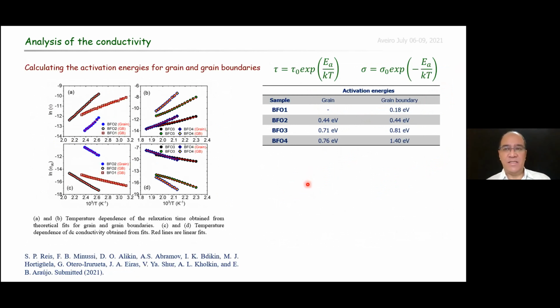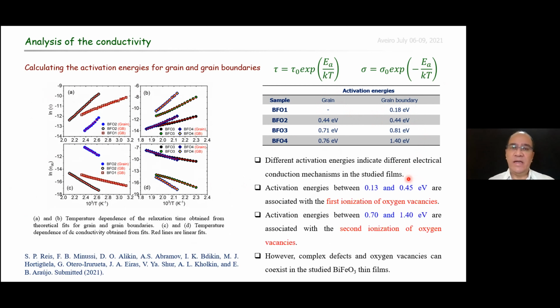From all these analyses, the temperature dependencies of relaxation time and DC conductivities of grain and grain boundaries were summarized in this figure. From the linear fit in all these curves, we summarized the activation energies in this table for the grain and grain boundary. Based on these values, the activation energies were associated with the first and the second ionization of oxygen vacancies.